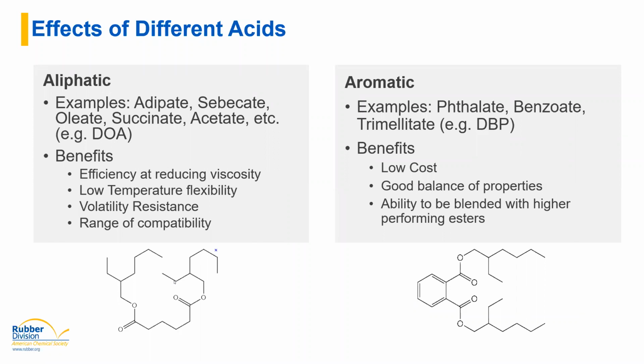used. So why would you use aliphatic versus aromatic? Aliphatics tend to be very efficient at reducing their viscosity, so less material is needed to bring that viscosity down. They tend to have much better low temperature flexibility than aromatics. They also tend to have very good volatility resistance, especially for their size, and they have a wide range of compatibility, especially being able to adjust the length of that carbon chain between the two ester groups. You can usually customize your compatibility pretty well.